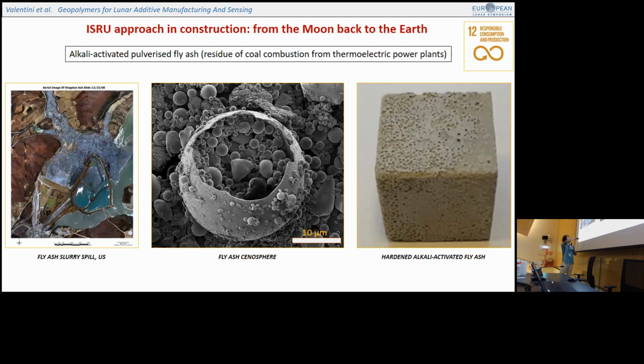Here you can see this event that occurred a few years ago in the US when some of this fly ash spilled from a containment pond and contaminated the environment. Okay, but if you collect fly ashes, it makes up a nice reactive powder made up of amorphous silico-aluminate particles, and when activated using alkaline solution, it can lead to the formation of a hardened material that can reach mechanical strength, compressive strength, easily up to 100 megapascal.